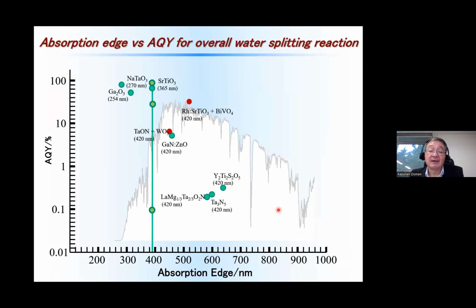Here I show our photocatalysts, which can split water into hydrogen and oxygen. And this brown colored dot indicates the 2-step overall water splitting system. And this axis shows apparent quantum yield in a logarithmic scale. And this axis shows absorption edge of the photocatalyst. And today I discuss a little bit in detail about strontium titanate, how to improve the activity like this one.